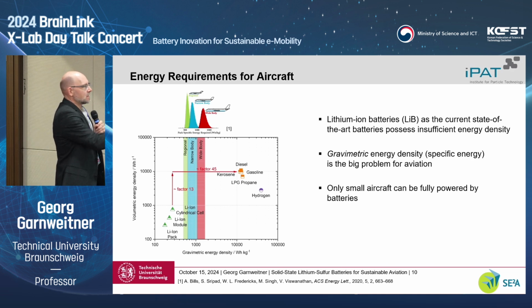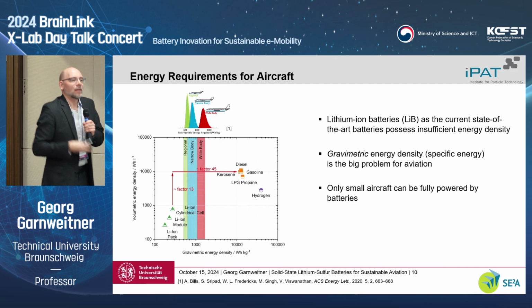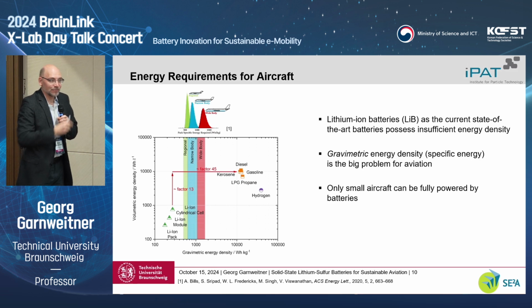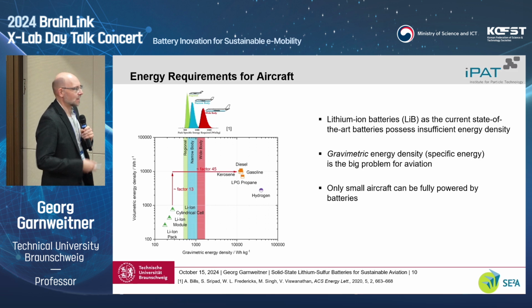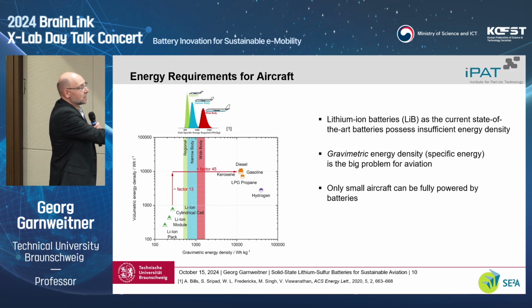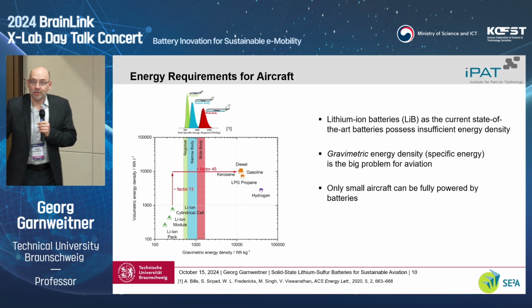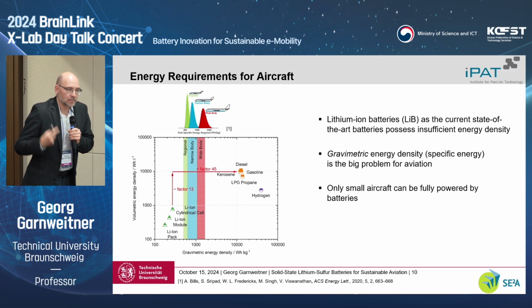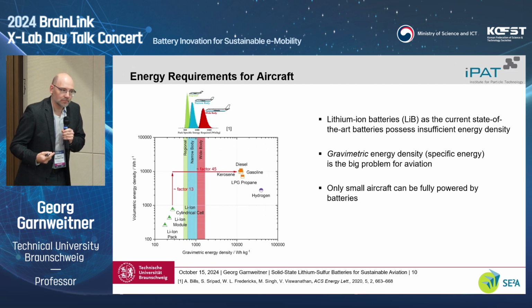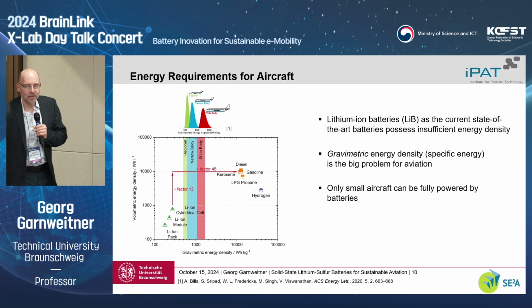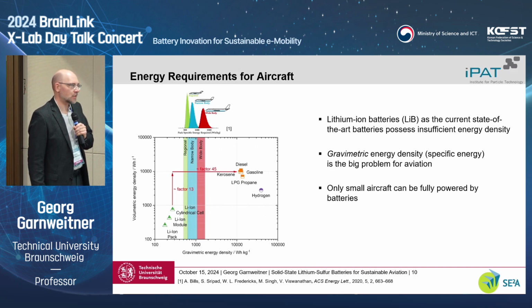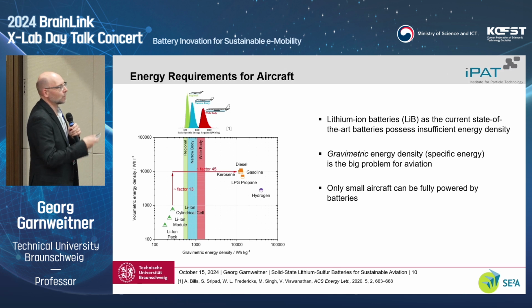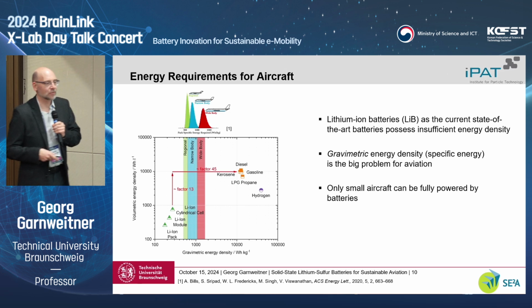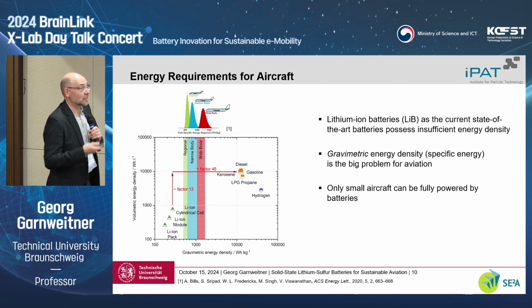Well, basically, here we have the so-called volume or volumetric energy density and gravimetric energy density. Actually, to be more precise, this would be the specific energy, as Mauro called it. So energy that we can store related to volume or weight. And of course, we see in this logarithmic plot that kerosene, gasoline, they are much higher than what we can store in batteries. This comparison is, of course, not entirely fair. On the one hand, we are comparing the pure substance that is burned to the whole system, where we reversibly shift the energy. But nevertheless, we see that we are orders of, or one order at least, 1.5 orders of magnitude below what we actually have in kerosene.